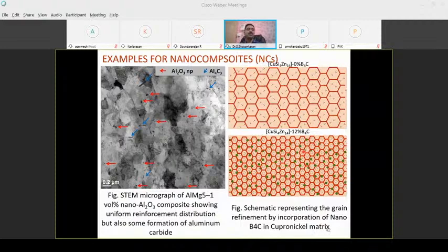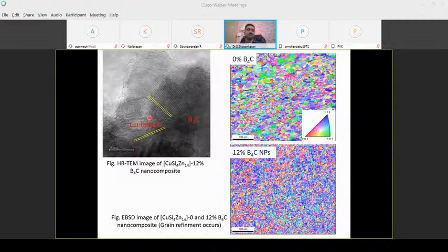And you see, this is an interesting picture: high magnification, high resolution TEM images. You know very well, whenever you decrease the particle size or grain size, there are severe lattice distortions. The atomic structure inside will be completely disturbed. So this is the composite, the copper lattice. The line indicates the d-spacing at the angstrom level. D-spacing means the distance between two atomic planes. And this is some boron carbide particles, and this indicates some grain refinement.